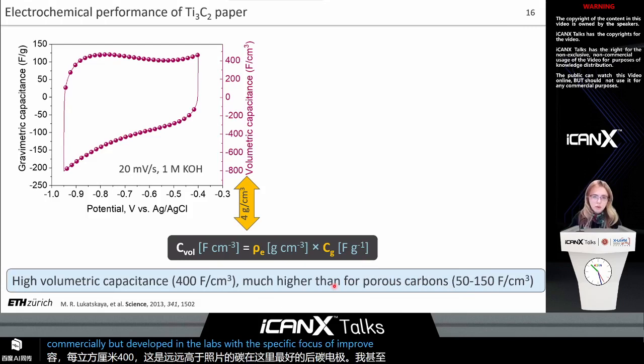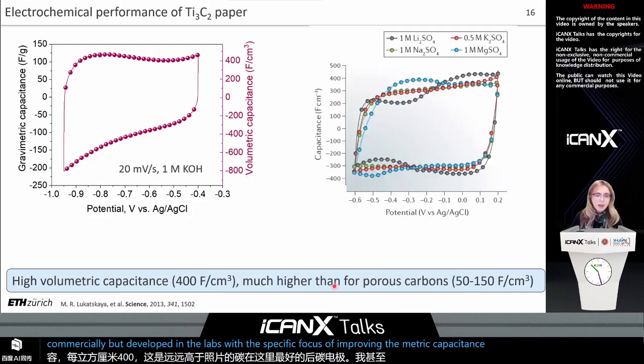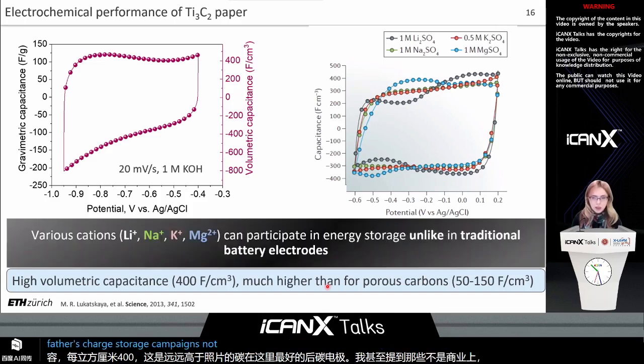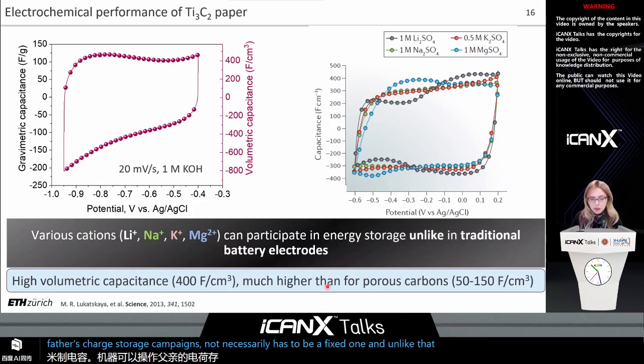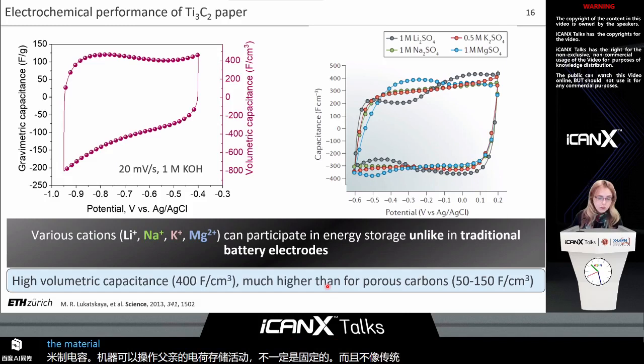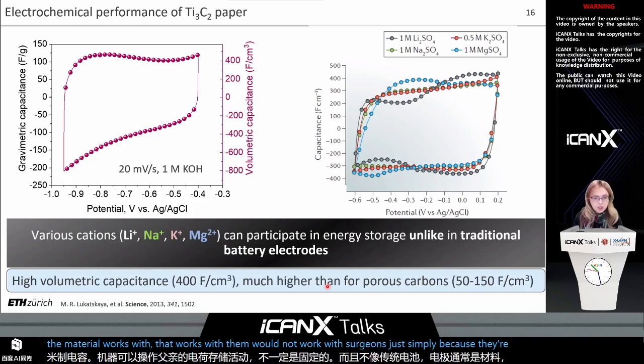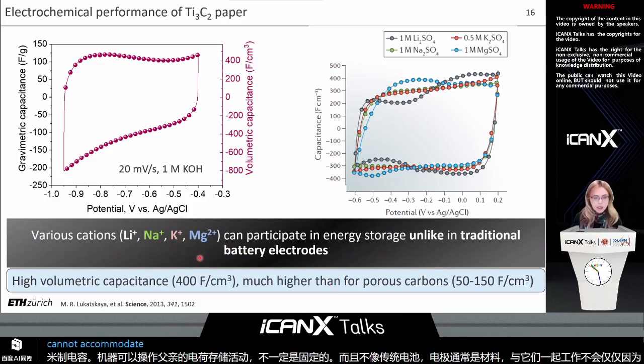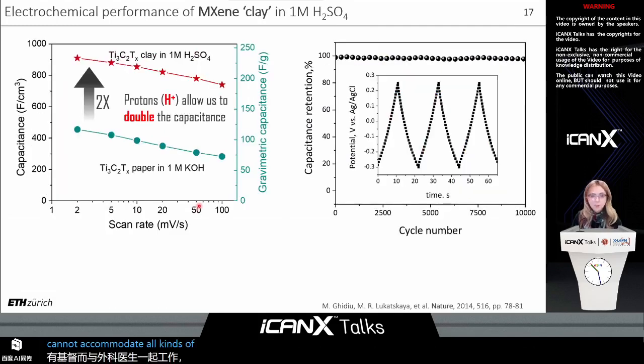improving the volumetric capacitance. Again, MXenes can operate with various charge storage cations, not necessarily has to be a fixed one. And unlike the traditional battery electrodes, where typically the material that works with lithium would not work with sodium, just simply because the crystallographic channel cannot accommodate cations of a larger size.